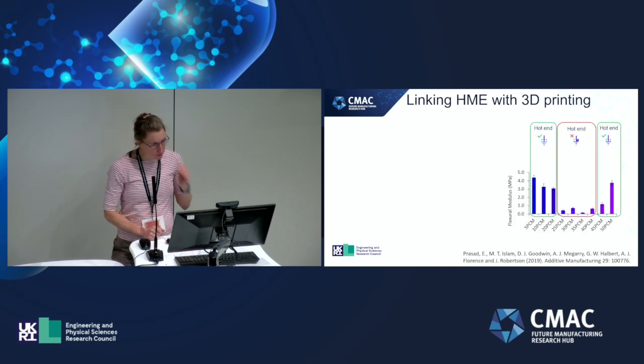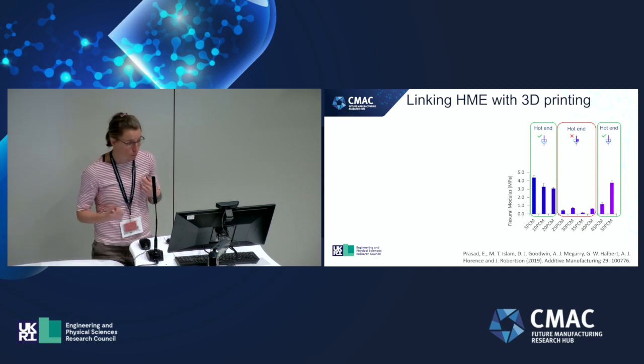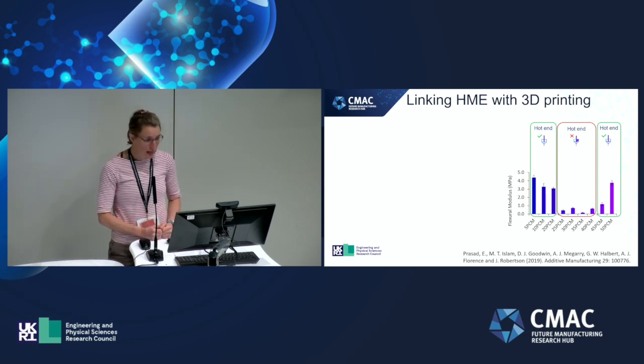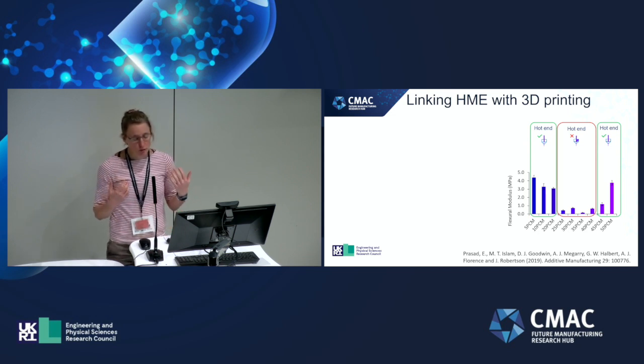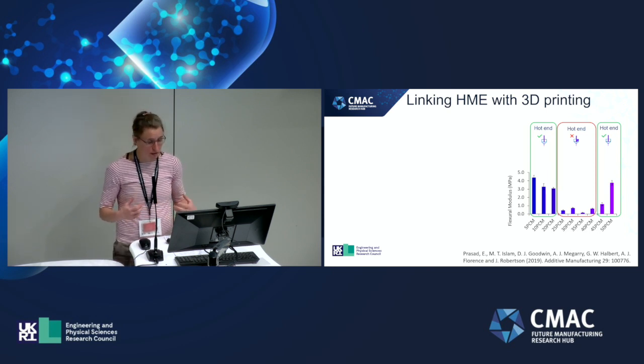So we have published some data relating to this two-step manufacturing process a wee while back in Additive Manufacturing, where we looked at a range of paracetamol drug loadings in an HPMC polymer, Affinisol, and what we developed was a screening tool to relate the material properties to the printability of these filaments. And we found that a big range in the medium drug loadings, 25 to 40%, failed to print due to ductile failure.